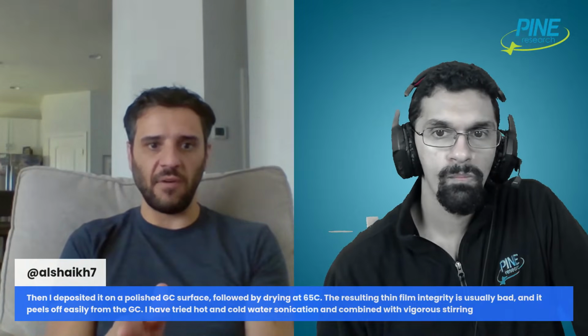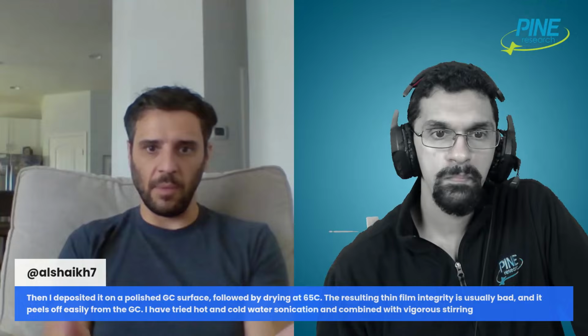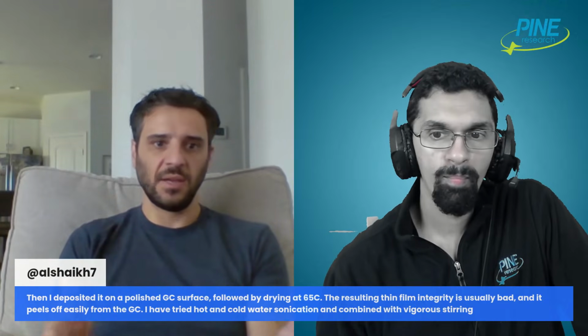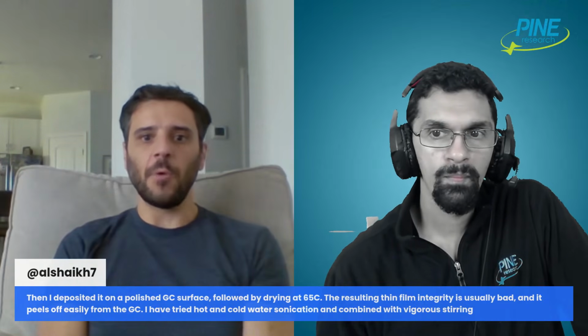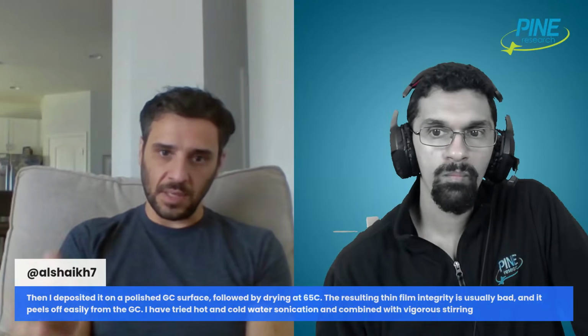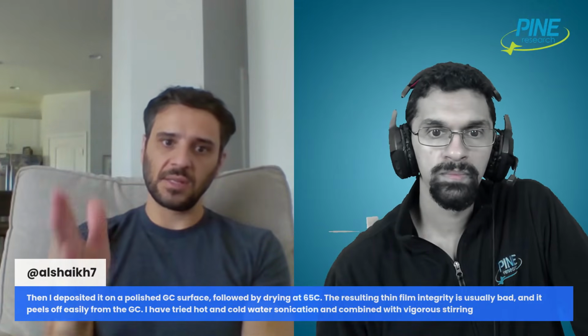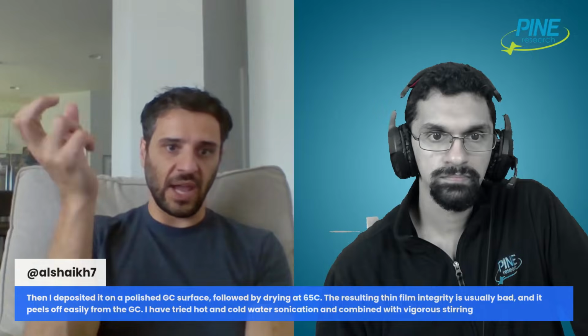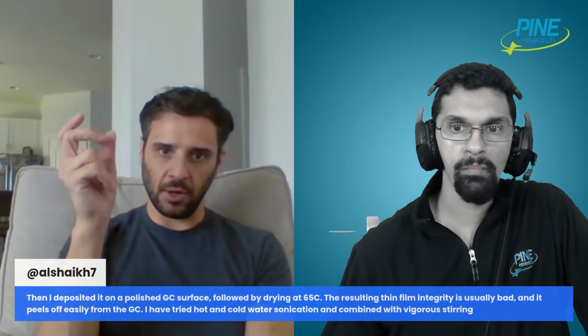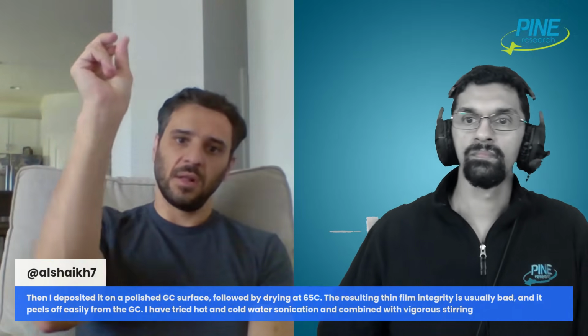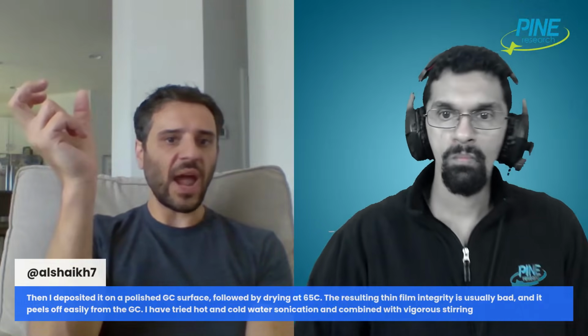Because if it's all falling off, who cares whether it was well mixed? If it's not staying there in the first place, you've got bigger problems. So make that ink of just your catalyst. Invert your electrode. Again, hopefully you're rotating it slowly while you're drying it. Make your droplet. Let it dry. You can just dry it at air temperature.